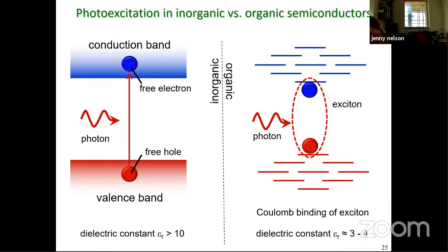I mean, what I could say is that if we just consider the place where we know, for the very fast processes, the high frequency epsilon will matter, but nevertheless, the performance of the solar cell is also very strongly dependent on the low frequency dielectric constant, because that will also control the interactions between the charge carriers, even when they're cold. And that will prevent them from escaping from each other, and will sort of determine the capture radius over which an electron and a hole can see each other. So it's still, at this level, quite an important concept.